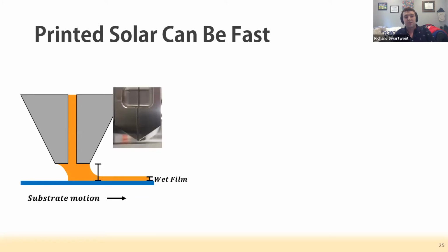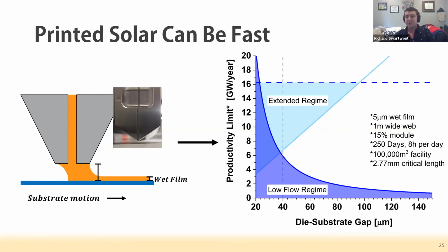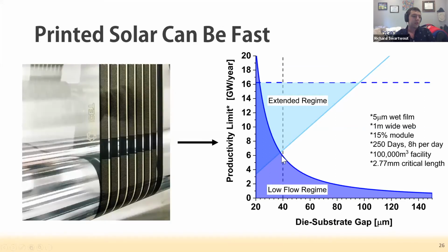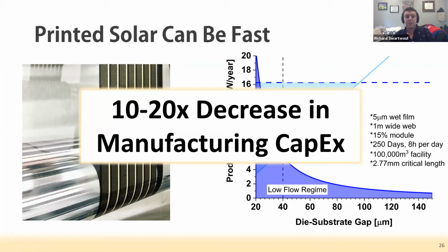And so just taking a very simple example of a slot die, which is one of the simpler printing based methods, you inject ink through a die, coat it onto a moving substrate. This process is defined by two main fundamental limits, the low flow limit and the extended flow limit. If you do some assumptions, I'm not going to go through the math today, but you can use these fundamental limits and calculate a productivity limit. And so if you're operating in the low flow regime, you can get up to about 6 gigawatts per year on a single tool. And with a little bit of structural shifting around with the die, you can get up to about 16 gigawatts per year in the extended regime. What this ultimately means, that combined with the cost of tooling, is that you're looking at about 10 to 20 times decrease in the manufacturing capex. And of course, this relates to the profitability of these materials because capex usually pins how profitable the technology ends up being.